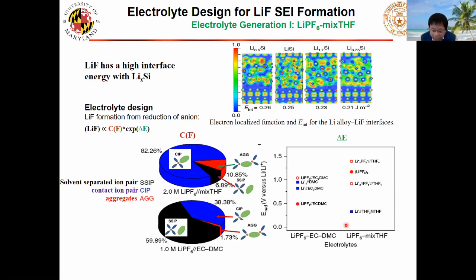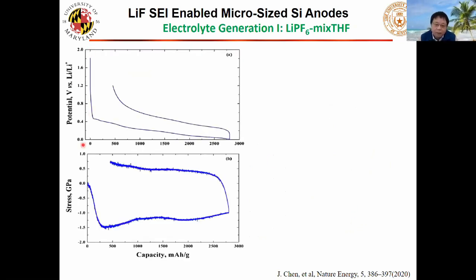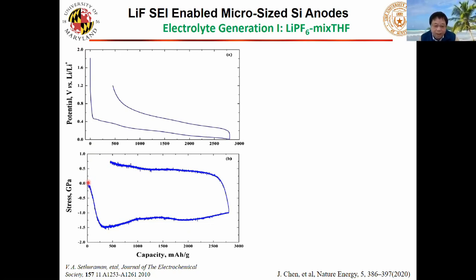This is a theoretical estimation. During lithiation, we also measured the stress. Because when lithium inserts into silicon, the volume change causes stress. Surprisingly, they find out that when lithium inserts to a certain level, the stress increases and then decreases. Why does it decrease? The reason is when lithium alloys with silicon to a certain value, they become plastic. So the volume supposedly should keep increasing stress with more lithium insertion, but it's not — it decreases because they have plastic deformation. Even with continued lithium insertion, there is plastic deformation. This means similar to lithium metal, lithiated silicon is plastic and they can flow inside a particle.